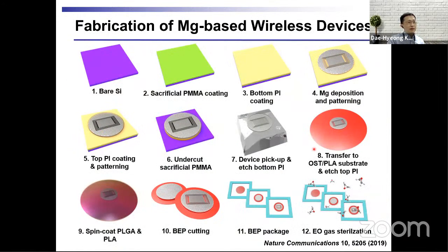And after making the drug reservoir, we separately fabricated the magnesium-based device, and transfer printed those devices onto the patch and cut the patch. And after fabricating this device, we packaged it and sterilized it with ethylene oxide gas. Note that we cannot use conventional autoclaving because hot steam may dissolve these magnesium-based devices. So instead of using hot steam, we used ethylene oxide gas for sterilization.